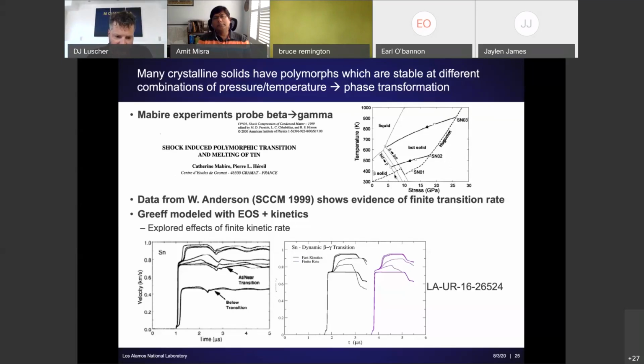So on the bottom of the screen are some velocity time histories for the shock loading of this tin material, experimental and then calculations. The experiments come from this publication from Mabire, where they were especially looking at a transformation from beta to gamma in tin. And then Carl Greeff in the theoretical division at Los Alamos has done some modeling of the beta to gamma transition. And so all of these curves here in black are using infinitely fast kinetics, which means that the equilibrium phase diagram holds. Whereas if you allow a finite rate of the kinetics, you can modify those waveforms that we're seeing.